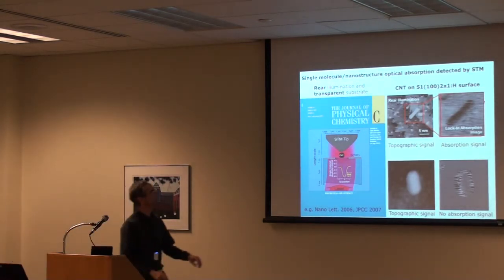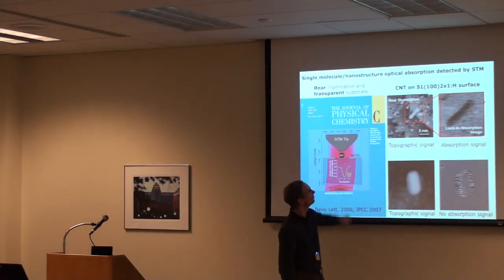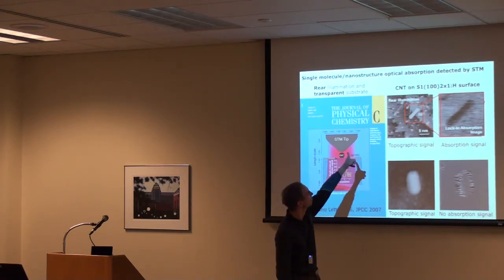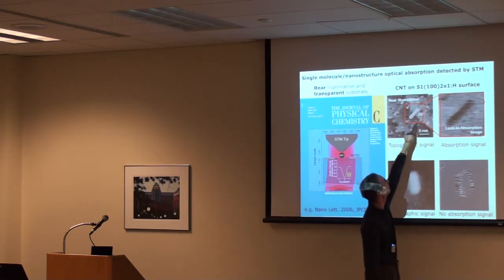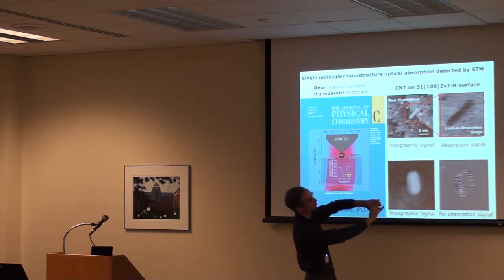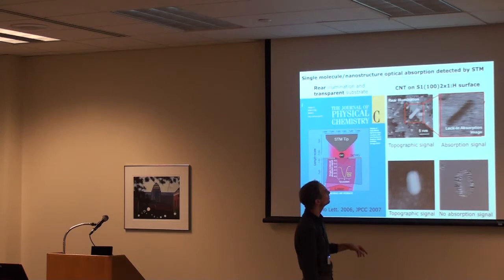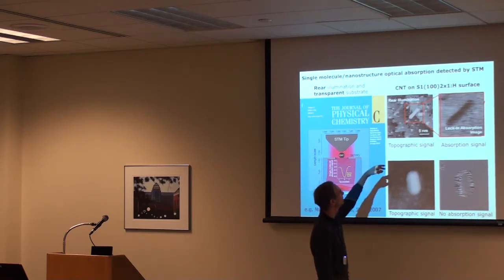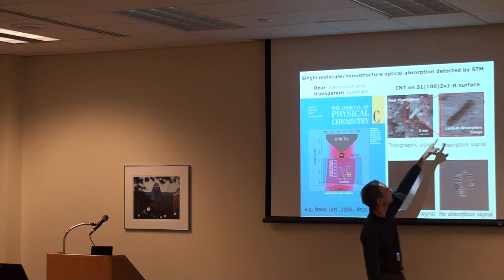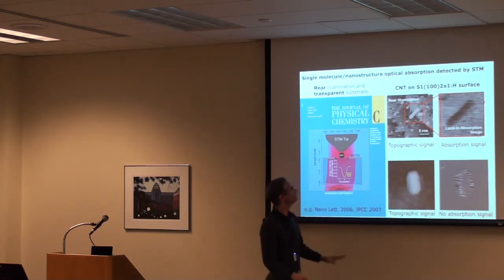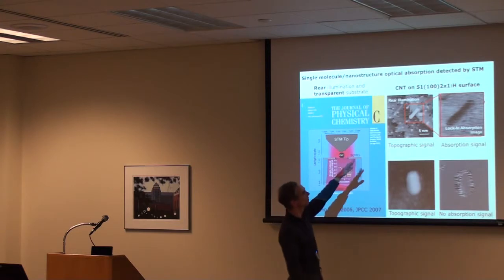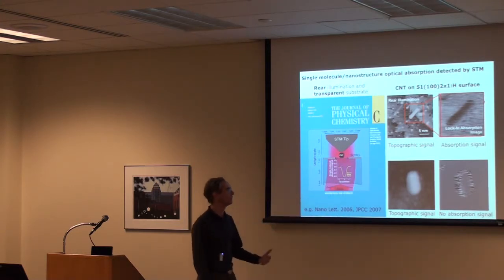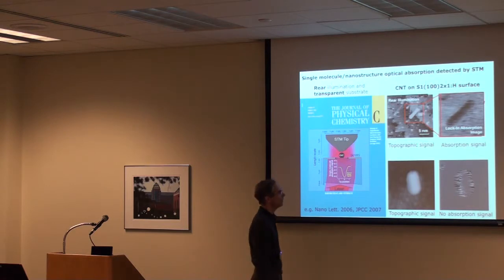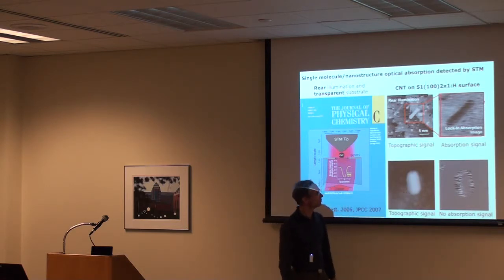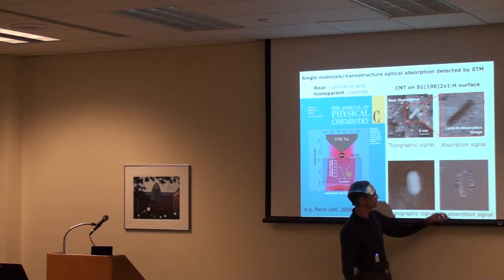So here's an example of a short piece of carbon nanotube sitting on a passivated silicon surface. You can see the dimer rows from the silicon surface. There's a step in the silicon surface over here where the dimer rows are perpendicular to one another. And if you measure an absorption spectrum of this carbon nanotube by tuning to the right wavelength, you see the absorption image here. When there's absorption, it's shown in black, and if not, it's a gray background. You don't see any of the dimer rows anymore because they're not absorbing. Instead, you see an image of the carbon nanotube. If you pick a carbon nanotube at the wrong wavelength and you try to measure the absorption image, you don't get any contrast. Here, it's the same gray on the carbon nanotube as what you get over here.